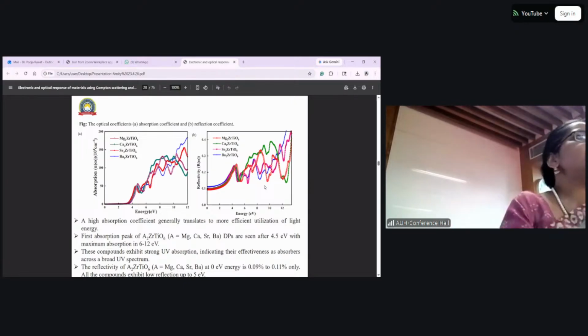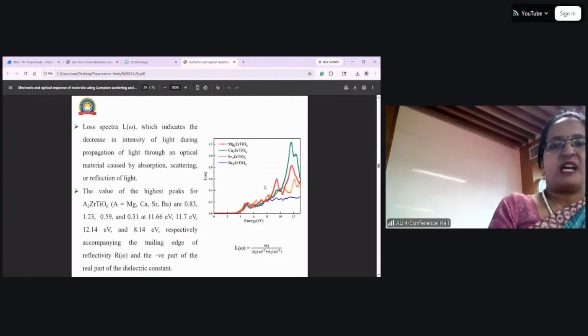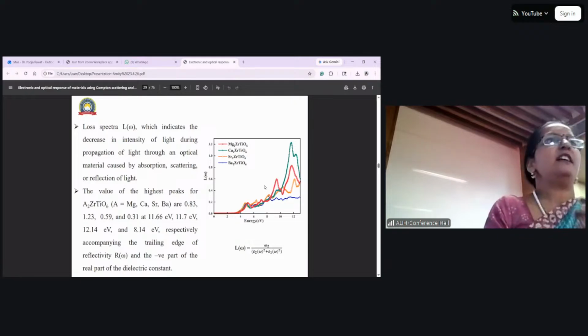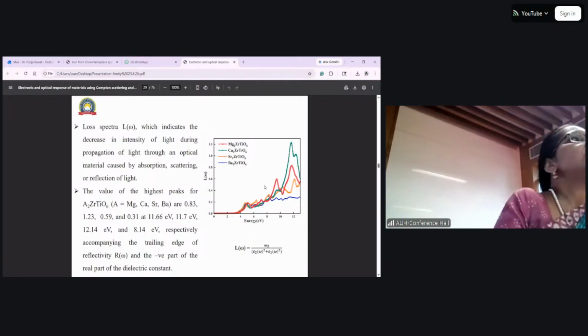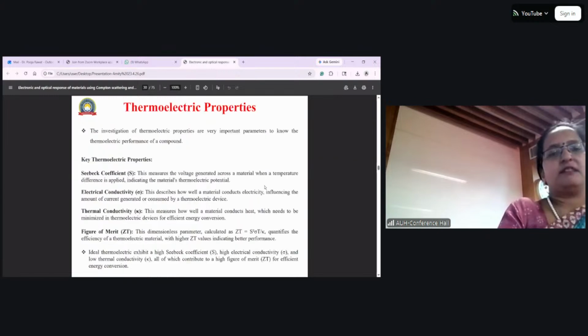Reflectivity: if I am forming a material, light should enter inside it and be absorbed, it should not be reflected. So we find that the reflectivity of these materials is very, very low. Then loss: if we are incidenting some light, how much of the light will be lost inside the material, that we have checked. For practical application, obviously this factor should be as small as possible.